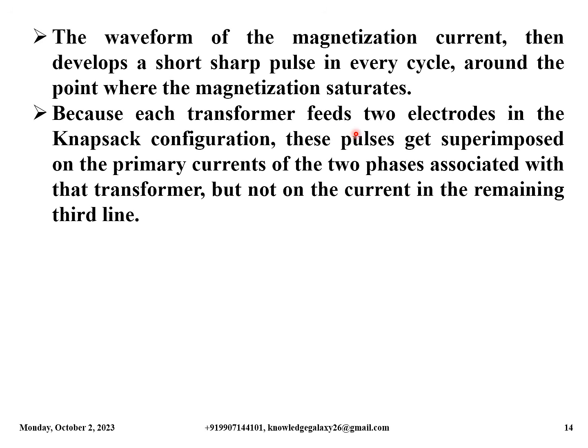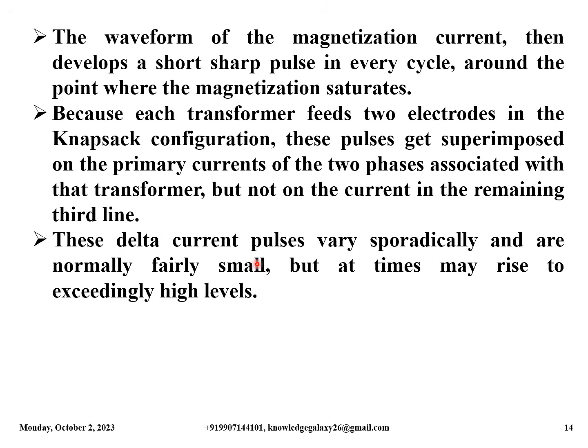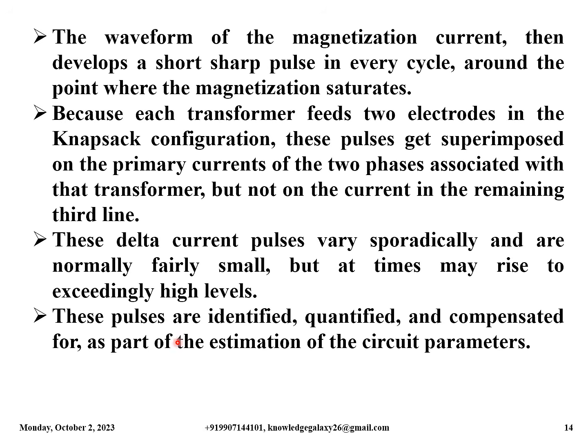Because each transformer feeds two electrodes in the knapsack configuration, these pulses get superimposed on the primary currents of the two phases associated with that transformer, but not on the current in the remaining third line. These delta current pulses vary sporadically and are normally fairly small, but at times may rise to exceedingly high levels. These pulses are identified, quantified and compensated for as part of the estimation of the circuit parameters.